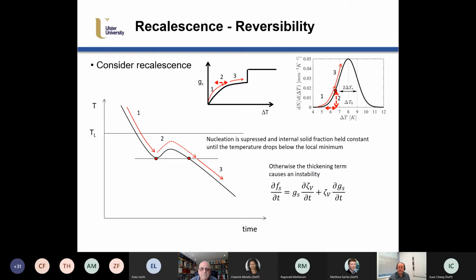A very interesting point that we discovered is the recalescence, and the model wasn't working very well until we made a deeper investigation into it. Essentially, the model was originally set up to be fully reversible, following both the nucleation and the Scheil curves faithfully, on both heating and cooling. But what we found worked best was that when you cool down and reach a saddle point, it starts to reheat because of the latent heat, and the growth continues. It's still undercooled, so the growth is still continuing, but we had to switch off the nucleation. The idea is that under recalescence the nucleation would have to go to 0, and only reinitiate when it reaches this point here at the end of stage 2. More importantly, we had to maintain the solid fraction during the recalescence phase.